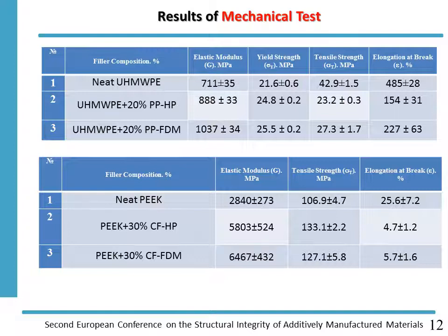A somewhat similar situation holds for the use of fused deposition modeling for the composite of polyether ether ketone loaded with 30% of carbon fibers. You see the value of elastic modulus is higher in contrast with hot pressing, there are nearly equal values for the tensile strength, and the value of elongation at break is about 1% higher.